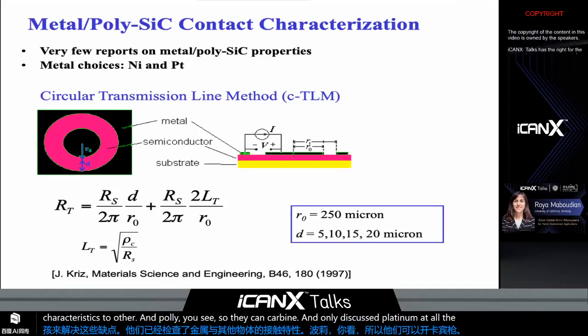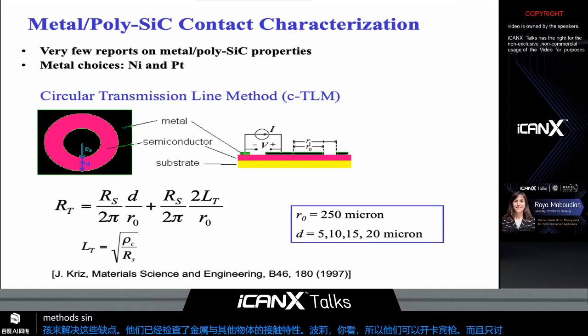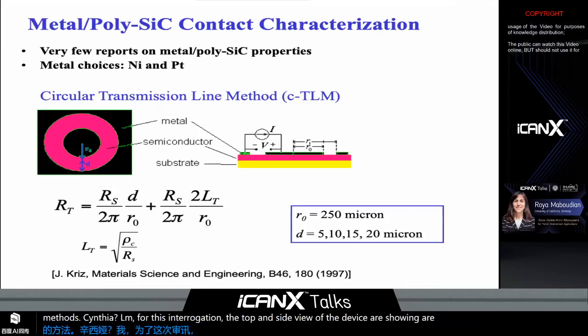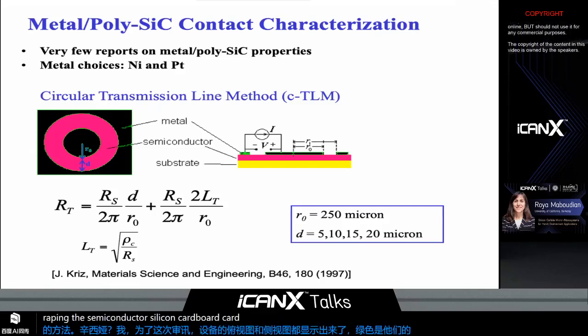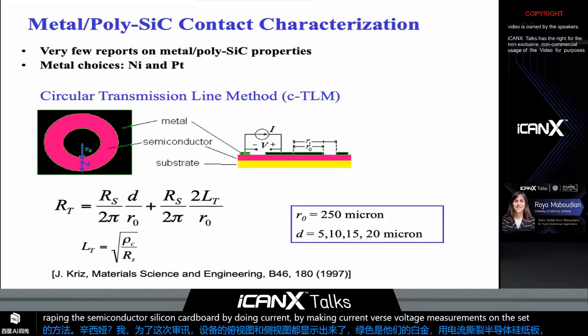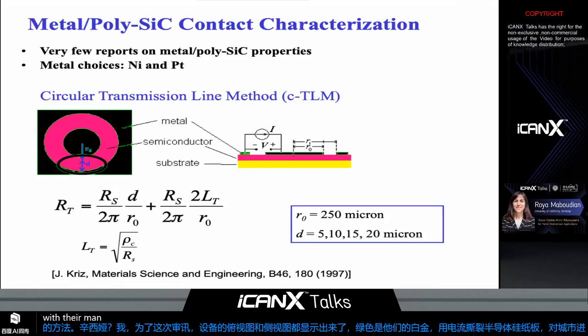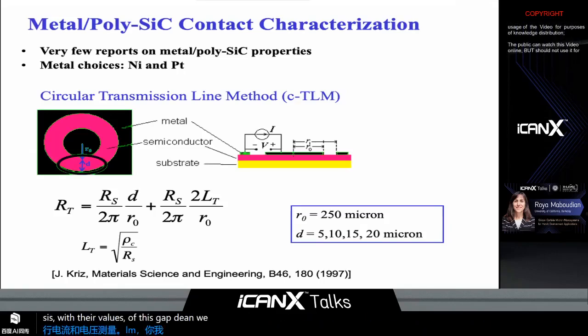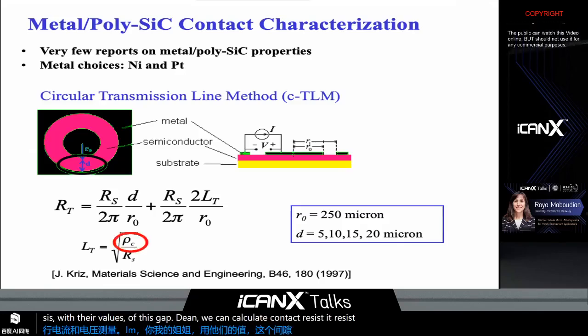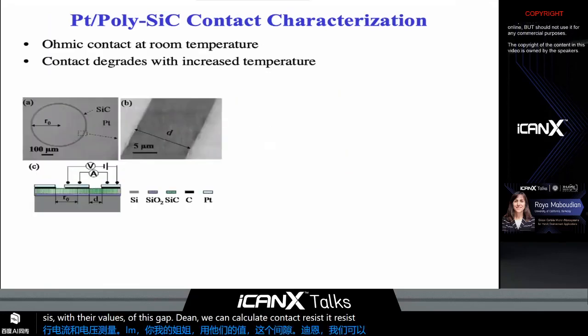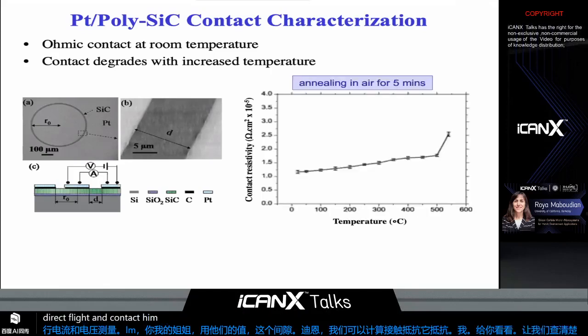We've used the circular transmission line method, CTLM, for this interrogation. The top and side view of the device are shown, with green being the platinum and red being the semiconductor silicon carbide. By making current versus voltage measurements on CTLM devices with different values of this gap D, we can calculate contact resistivity, rho C. Let me show you what we found out. Here, let's look at the results for direct platinum contact to silicon carbide.